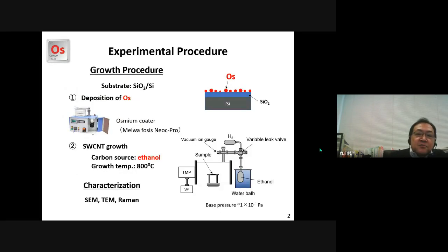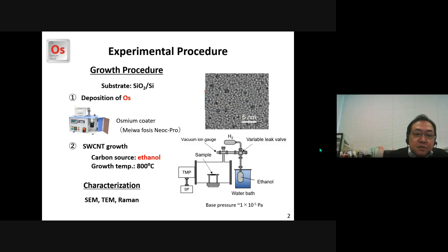We also performed single-wall carbon nanotube growth using osmium as catalysts. In this experiment, osmium was deposited on SiO2 silicon substrate by using an osmium coater, which is widely used for the sample preparation of SEM observation. Then SWCNT growth was performed by ACCVD. Next slide, please. Using osmium catalysts, we succeeded in vertically aligned SWCNT growth. Next slide, please.